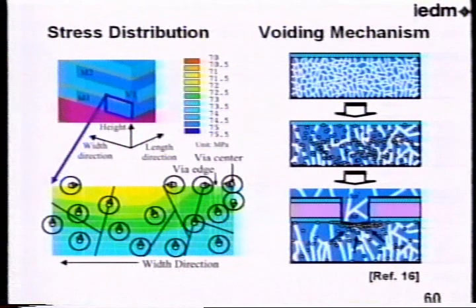I think this stress migration reliability is caused by the stress distribution of the metal like this. First, this is the electroplated copper film. After some heat treatment, the grain growth is proceeding like this, but there are many defects like this. In the thermal treatment, these defects accumulated at an interface between via and line will make some void in lines. So there is this kind.